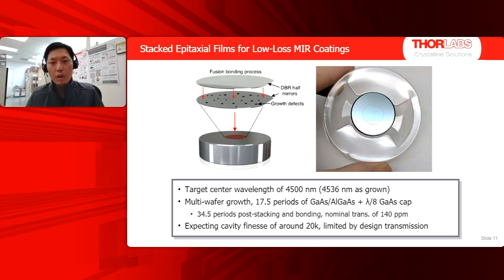But of course, at these long wavelengths, the total thickness that you require due to the longer wavelength, as well as the number of layers that you need in order to achieve low transmission, really pushes the limit of that growth technique, and it becomes an unstable growth, and you can't reliably get multi-layers that way. So we have this cute trick where rather than grow the entire design stack in a single MBE growth, you actually just grow half of it, exactly half of the design.